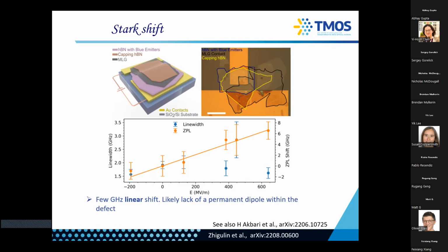The results here are actually quite interesting because you will see that there is a few gigahertz linear Stark shift. So only a few gigahertz. So remember the previous Stark shifts for these red emitters were massive, nanometers. We can shift them.